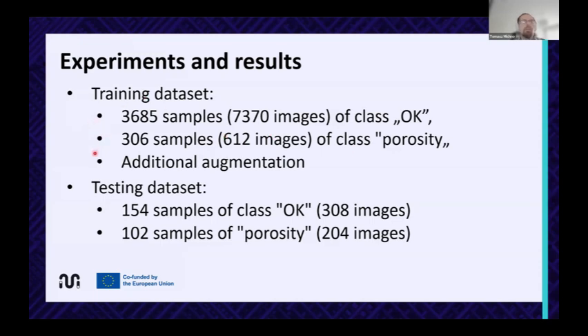Because of that, we made some additional augmentation in order to improve this number of bad class, but still, yes, the training data set was a bit imbalanced. And for the testing, we used 308 images of good parts and 204 images of porosity class. So these are quite big numbers in case of the total number of samples, but yes, we have different proportions.